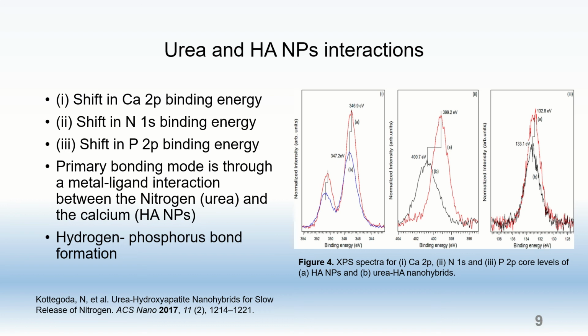And this is indicative of a new bond being formed between the urea and the hydroxyapatite nanoparticles through the nitrogen atom of the urea. When looking at calcium 2p XPS spectra, there is also a noticeable shift towards a higher binding energy. This suggests that the chemical environment around the calcium 2+ ions in hydroxyapatite is changed in the presence of urea. Also, there was a small shift in the phosphorus 2p core level spectra, which is possibly due to the forming of hydrogen bonds between the phosphorus groups of the hydroxyapatite nanoparticles and urea.